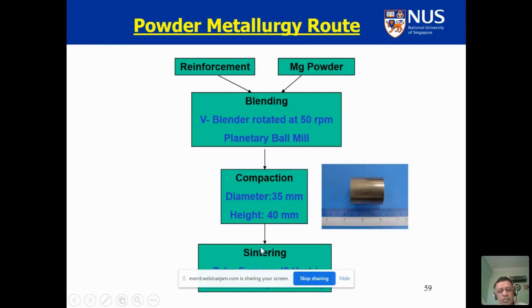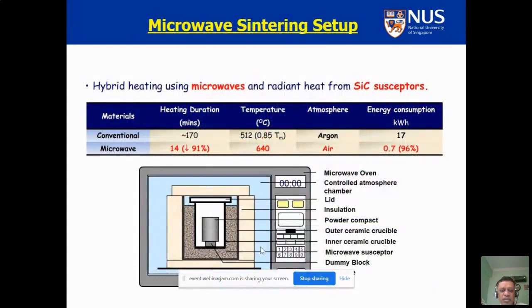You can do the sintering using the conventional tube furnace or the box furnace, or you can use a microwave. We use microwave because we want to save energy. So what we did was that we took a microwave which is used in the home and created a setup to be put in the microwave, where you can see in the center is a billet, inner crucible, microwave susceptor, outer crucible, and the dummy block.